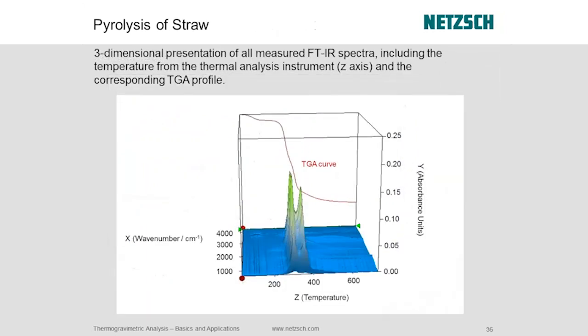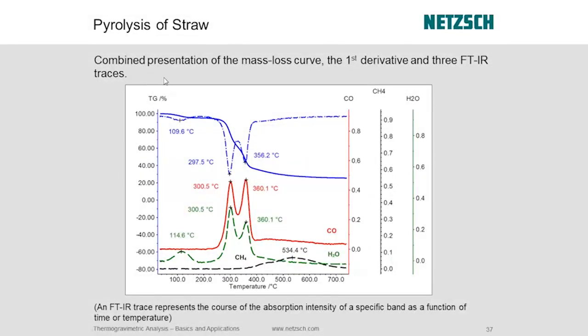If we connect that to the FTIR, we can get, at the same time as we're getting our mass loss curve, the evolution of the gas species by the FTIR. So here we see that with the pyrolysis of straw, a presentation of the mass loss curve, the first derivative, and then three different FTIR traces that we're tracking over time. So here's our mass loss profile in blue. This is the differential, so we see these mass loss steps more clearly. But now we look at the FTIR traces, and we can track these individual bands, these individual spectra as a function of time. So we get a continuous plot of the evolution of these gases, and we can kind of see then where they correlate to the mass loss in the TGA.